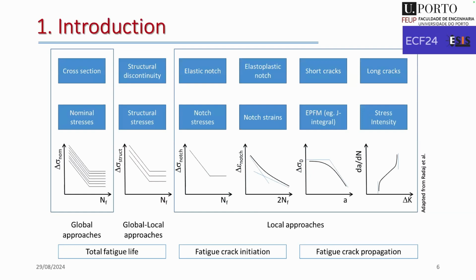So we are talking of using notch stress approaches, elastoplastic notch strain approaches. We are also always using the possibility of exploring fatigue fracture parameters to address short fatigue cracks or long fatigue crack propagation. So this is a very wide field of possibilities that allow us to address fatigue damage, for example, into different, let's say, stages of evolution.